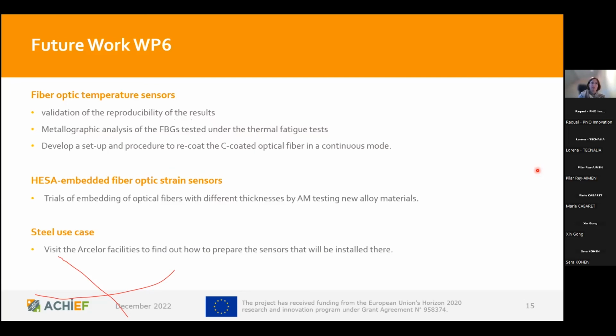And here I've shown you the remaining steps for our work package, and that is to actually validate the reproducibility of the results, continue with or finalize the thermal fatigue tests, and also develop a more continuous mode to coat the carbon coated fibers with the metal coating to go to larger scales.